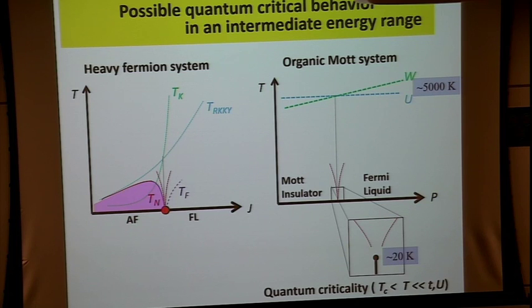In our case, the Mott transition is not associated with symmetry breaking. So, as you say, the first order transition will cross over, and the first order transition occurs at low temperatures. However, the first order transition has a very low critical endpoint, 20 Kelvin. But the competing energy is 5,000 Kelvin, a very huge energy scale. So why not quantum critical behaviors even in first order transition systems? And in reality, indeed, we observed quantum critical behavior in this. So we think that a quantum phase transition is not a necessary condition for observing quantum critical behaviors, even when the transition is of first order.